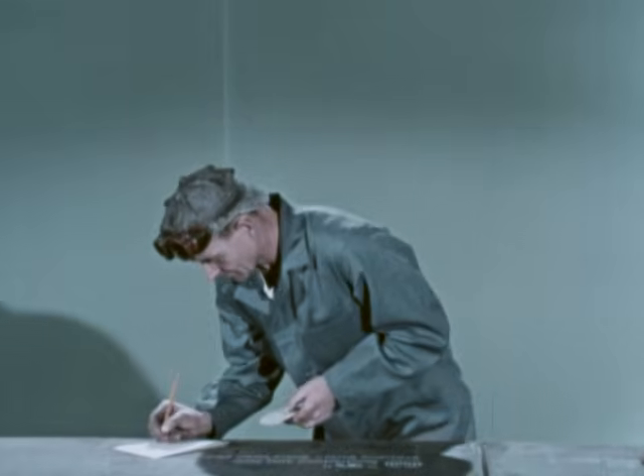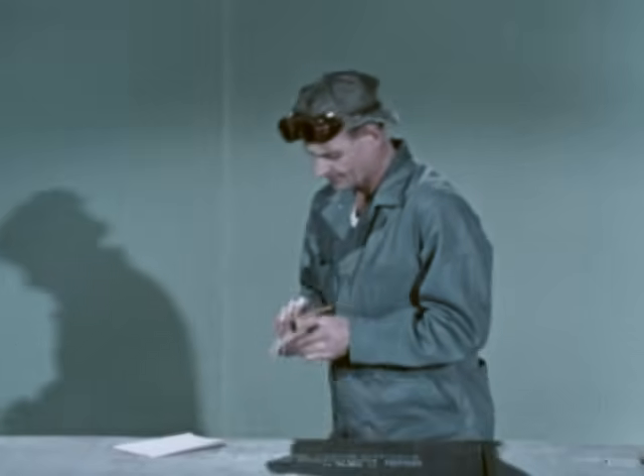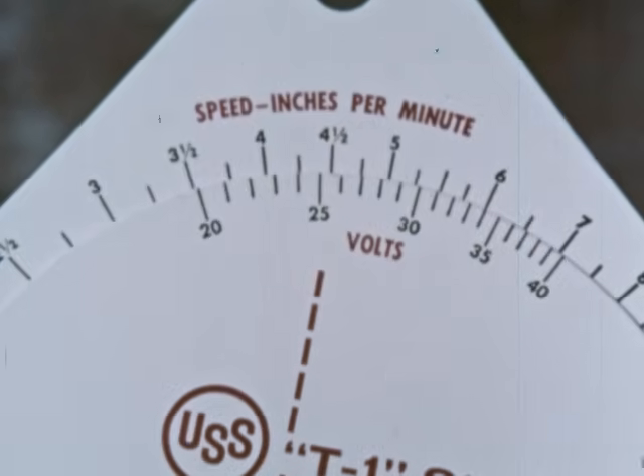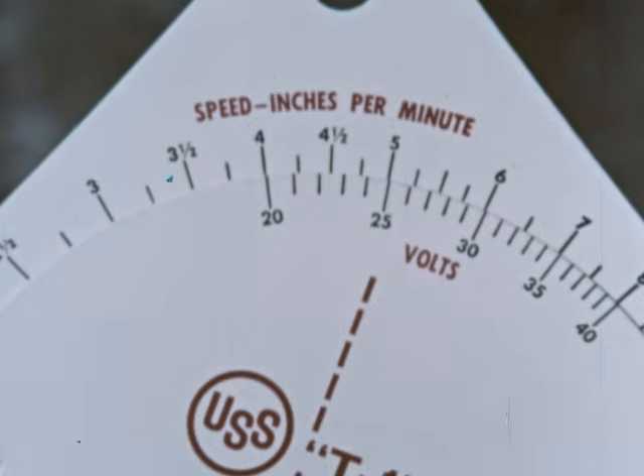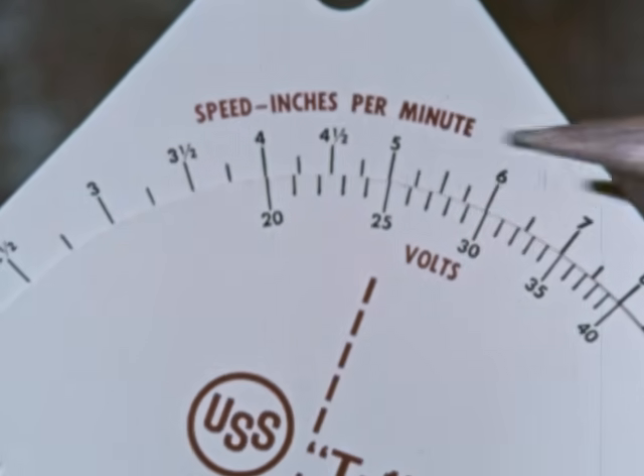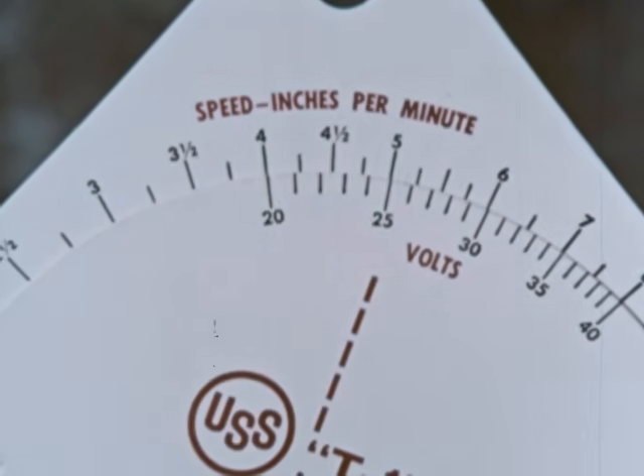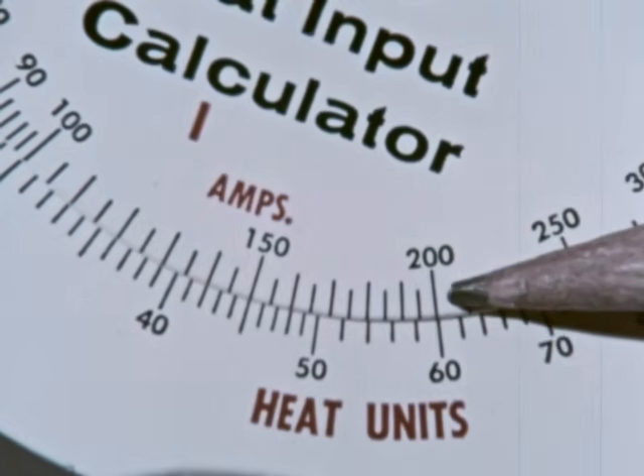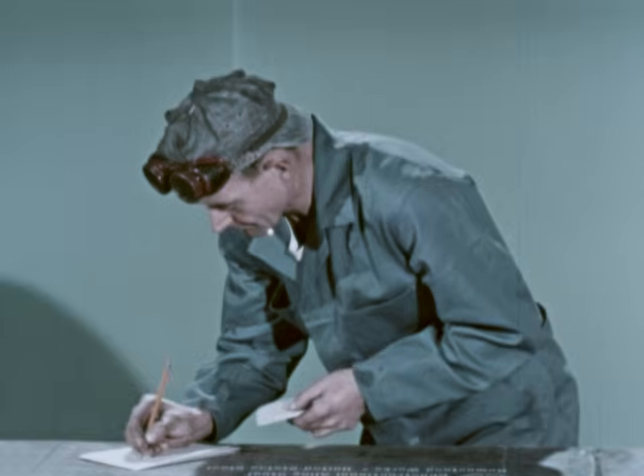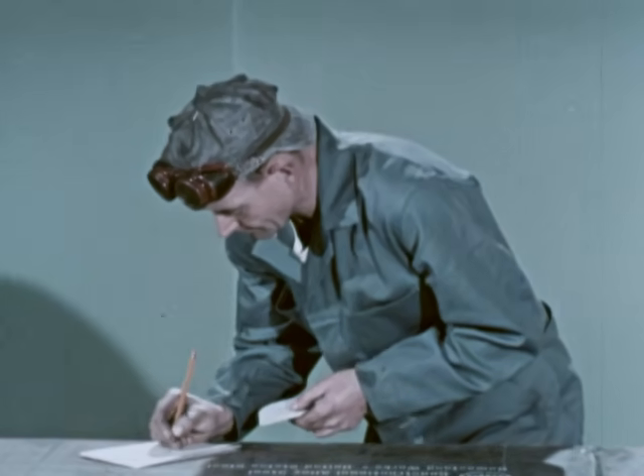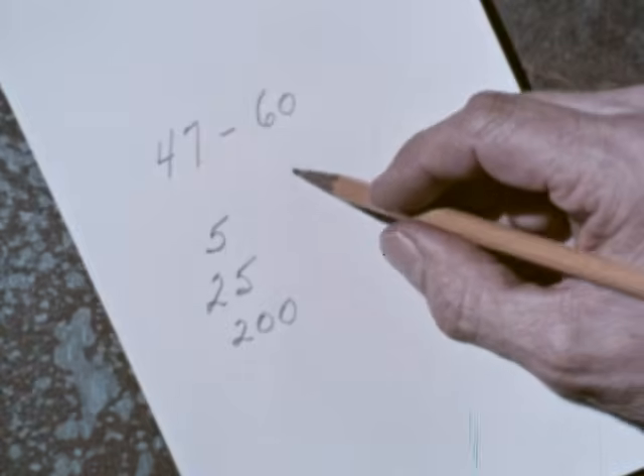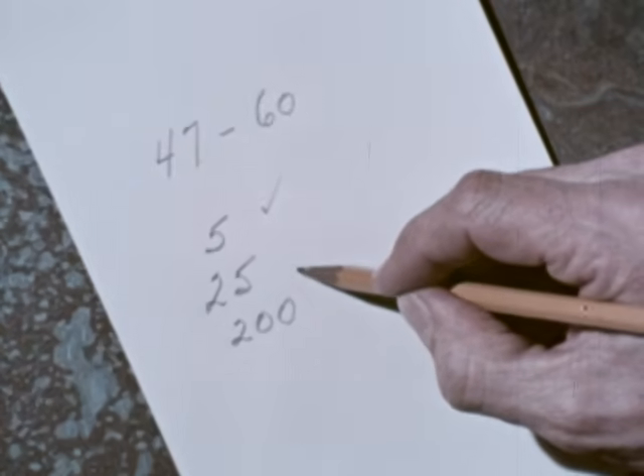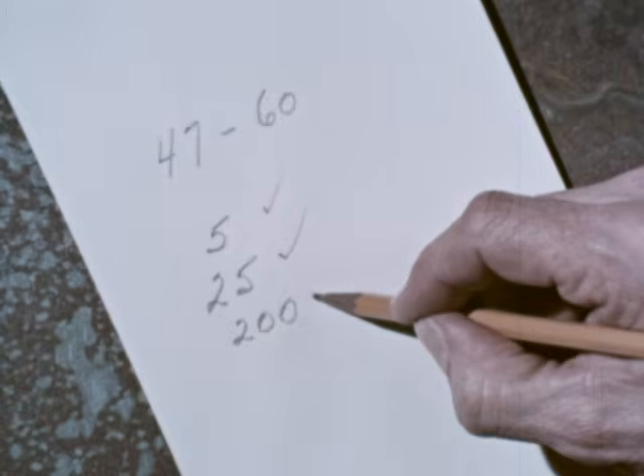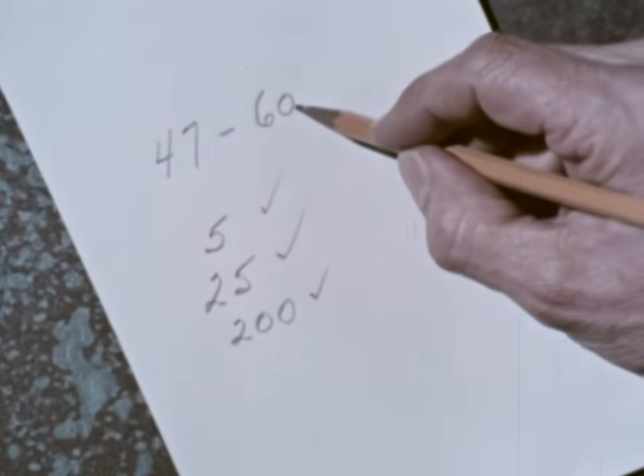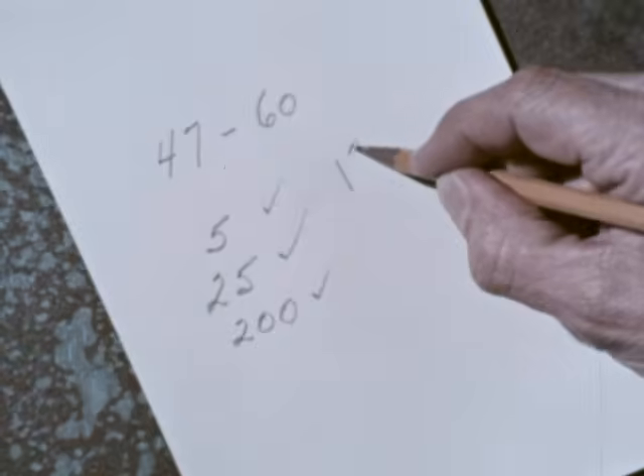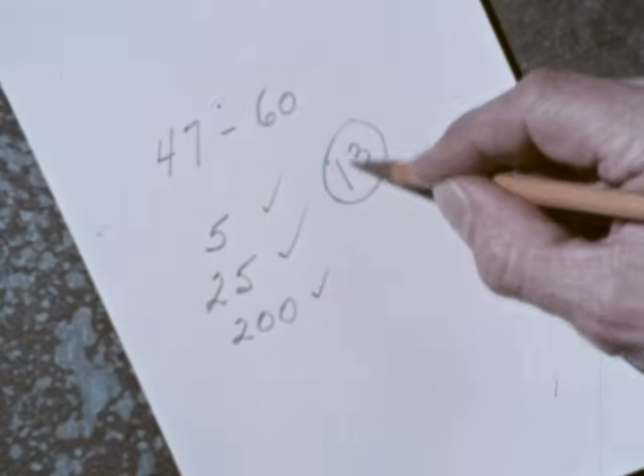Now, set the calculator at figures you might consider standard, as you do in any welding job. In this case, you've selected a speed of 5 inches arc travel per minute, a voltage of 25, and an amperage of 200. So you put down all the figures and make some comparisons. Your 3 conditions, 5-inch arc speed, 25 volts, 200 amps, result in 60 heat units, 13 units higher than the suggested maximum of 47.